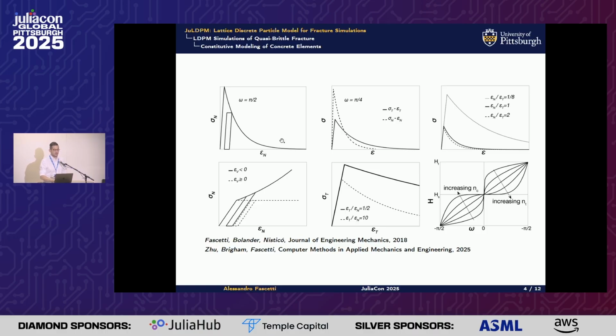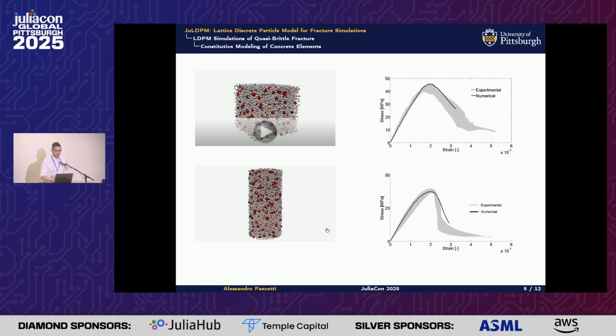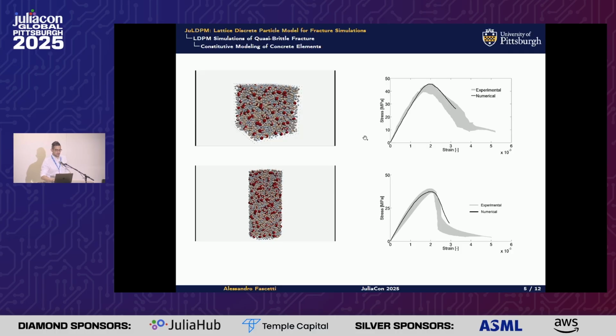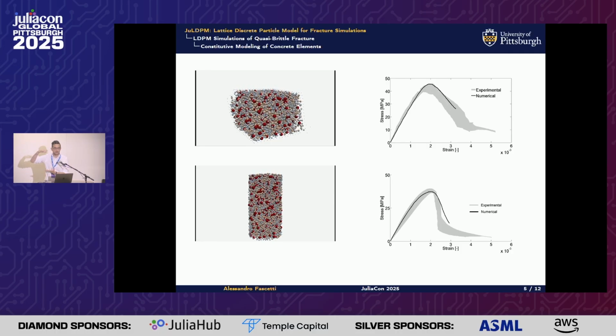So you see some of them here for tensile behavior, shear interaction with tensile behavior, where the different levels of compression basically provide more frictional resistance to shear fracture at the lattice element level, and so on and so forth. If you're more interested in the details, which I'm going to have to skip, please refer to some of these recent papers that my group published. But in practice, I want to give you more of a flavor of what the simulations look like. Effectively, you have this very dense pack of particles.